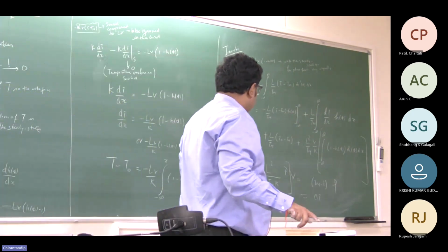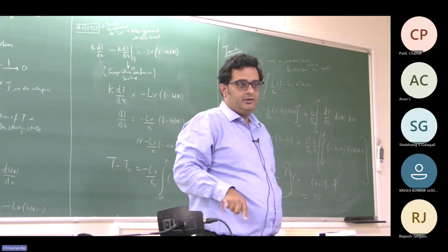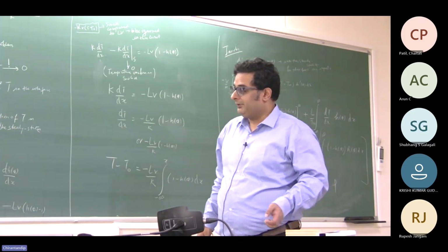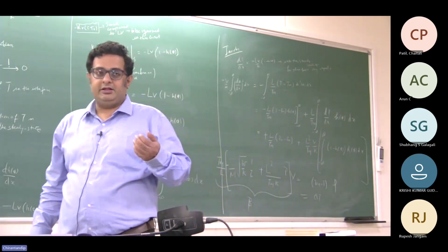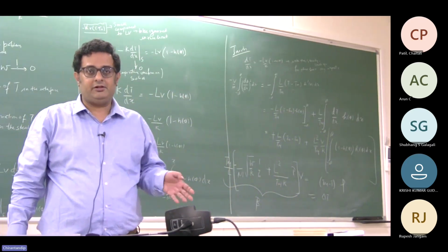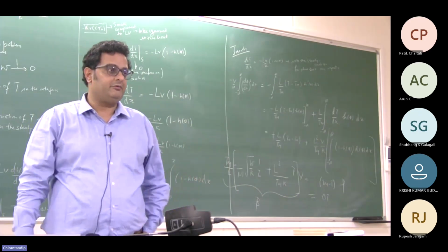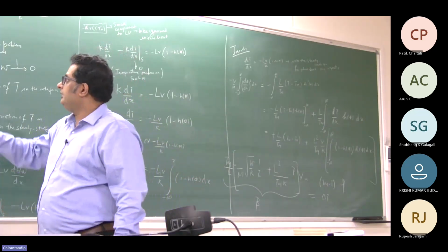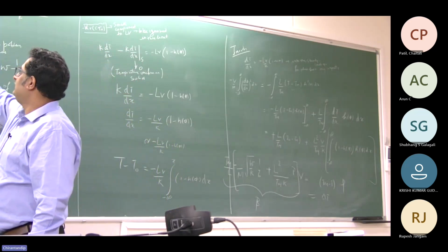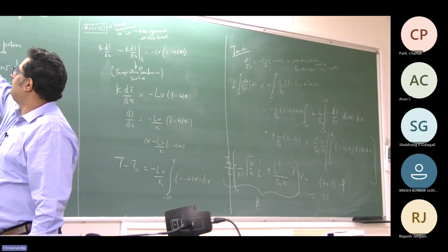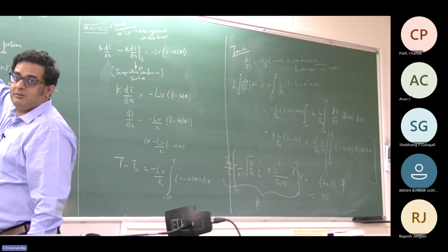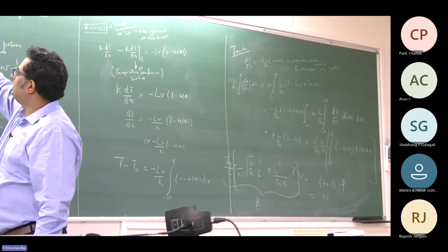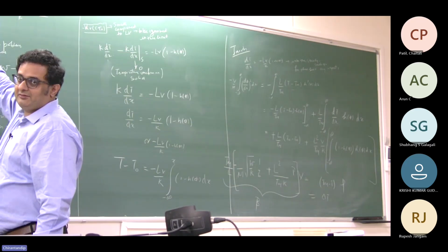Now, that's all good for the case of heat. But as soon as you want to do something with mass, you typically have the situation that the diffusivity of the solid is much smaller than the diffusivity of the liquid. That gives rise to the situation that in an interface, if you have flux, the flux is able to escape faster here, but less here because it is closer to the solid. So your effective mass diffusion is reduced on the solid side and enhanced on the liquid side.